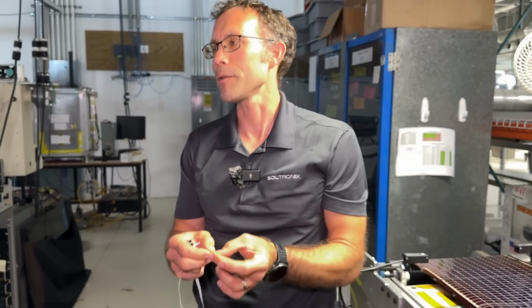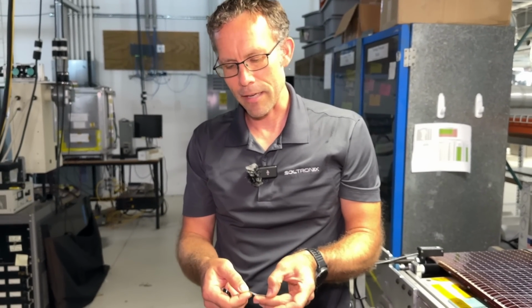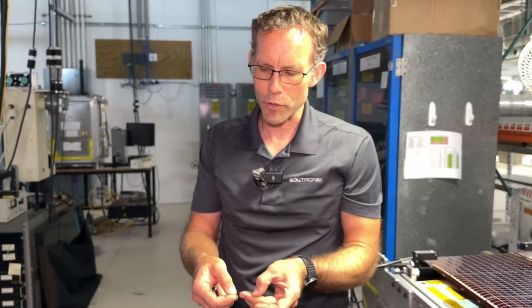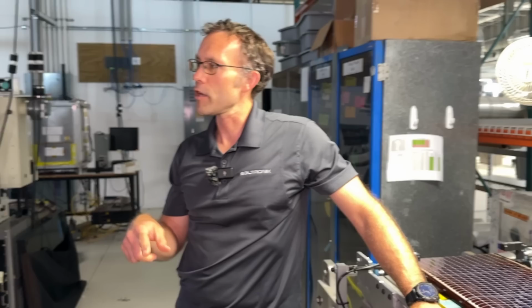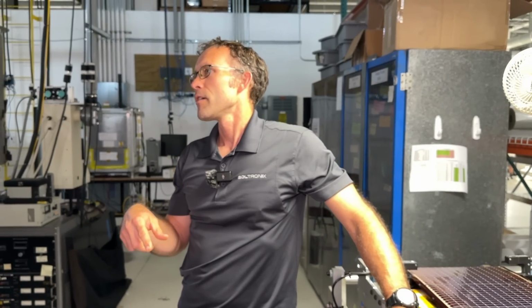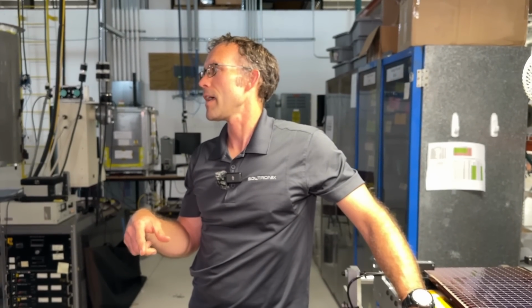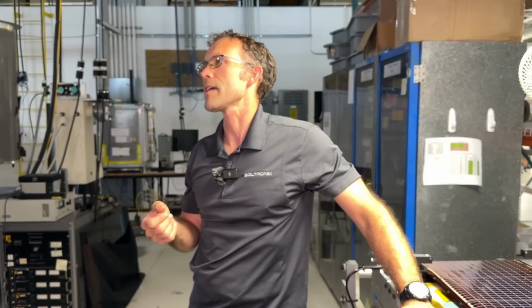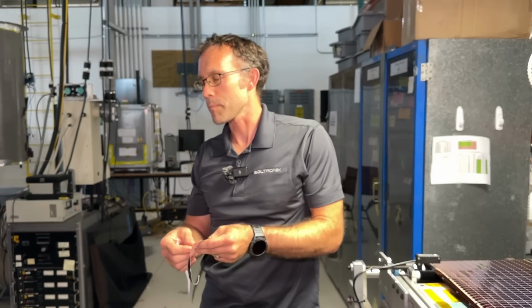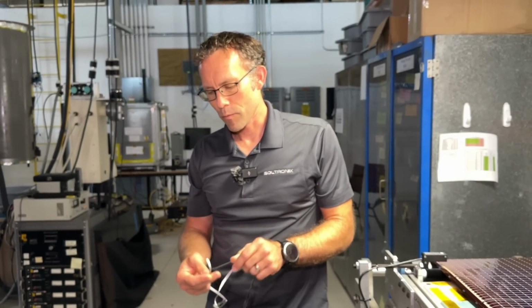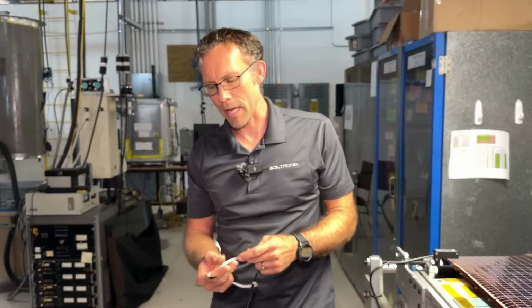It's incredibly durable. I mean, we run these things to a couple thousand roll cycles, 2,000 to 3,000 when we test. And what that means is it goes over a 3-inch roller and a 6-inch roller 2,000 to 3,000 times. And you know, stick them back out, take them outside, test them. There's no degradation. You know, it doesn't peel away. It's really held in place. And so it's some really cool tape.